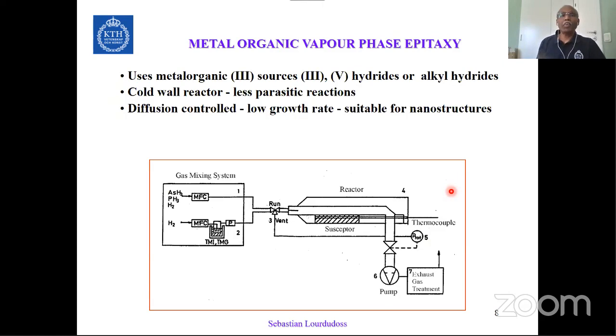So in metal organic vapor phase epitaxy, it basically uses metal organic sources, for example, for 3-5 compounds, metal organic group 3 sources, and group 5 hydrides, arsine and phosphine, or alkyl hydrides. Basically, it is a cold wall reactor, with fewer parasitic reactions. It is diffusion controlled, with a low growth rate.